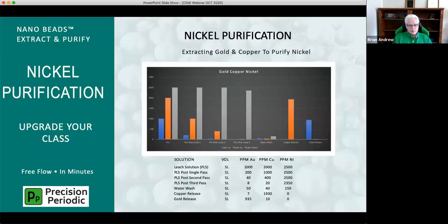Let's get on. Another way to use this, the description I've given you so far, is where we have a filter program to explicitly pull out gold, for example, and mercury. But we can also program the filter to not pull something out. In this case here, the leach solution is a very, very strong nickel sulfate. And in this case, it's polluted by copper and also by gold. And so they want a class one nickel. So rather than process the nickel, extract it from the PLS, we extract the pollutant from the PLS.